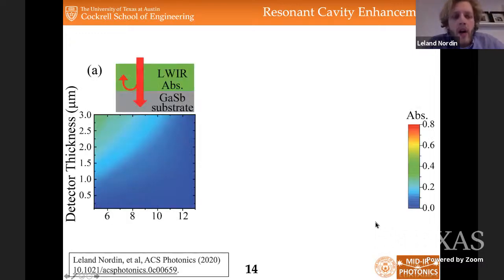Well, if we leverage that high reflectivity, we might be able to grow a resonant cavity, similar to how that photoluminescence was enhanced. So if we look at the detector thickness versus wavelength for just one of these T2SL absorbers on top of a gallium antimonide substrate, you can see we have rather low absorption efficiency, around 10 to 20%, where typical infrared detectors are upwards of 60%. This is almost completely a consequence of the fact that the hole and electron wave functions are spatially separated in a type 2 superlattice. So they have a rather low absorption coefficient, meaning that it would be beneficial to enhance their absorption through some sort of plasmonic enhancement.